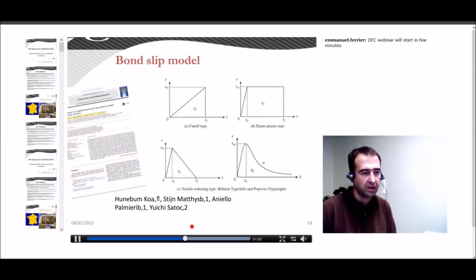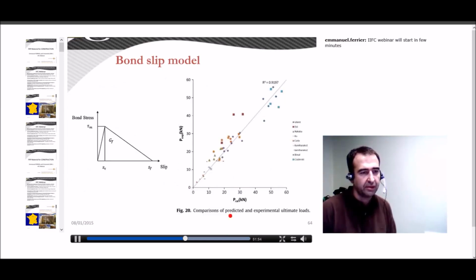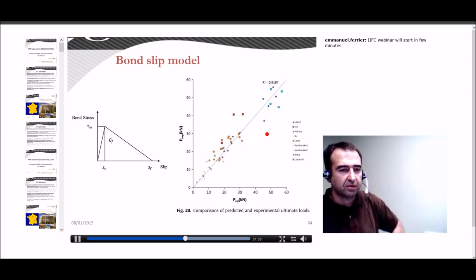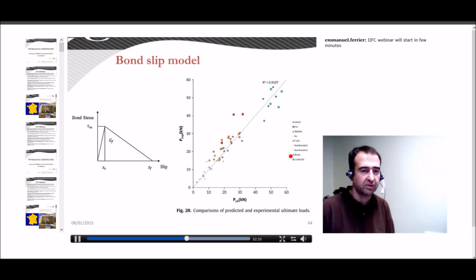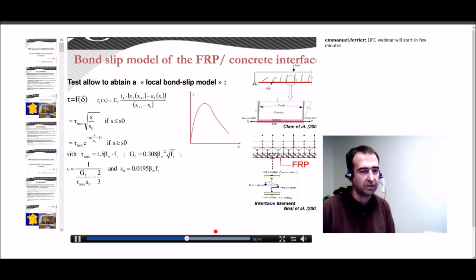A comparison has been done by Stijn Matthys and Aniello Palmieri. This study is very interesting because you compare a lot of tests. If you have to develop some bonding issue, I recommend you read this paper because you have a lot of results coming from the literature and a comparison of the ultimate calculated value and the experimental one, clearly showing that the calibrated models are quite good, depending on the test and the fitting you get. We can observe quite good results, whatever the mechanical relation used.